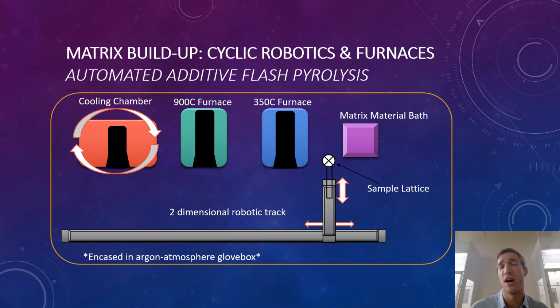Now, I mentioned this automated system that we're using for this project. Here is a basic schematic of how this system operates. It's enclosed entirely in an argon glove box that's positively pressured, and there are 4 different stages. The first stage is the material matrix bath, or smart syringe deposition, which deposits a diluted polymer precursor onto the sample, which is either a woven lattice of fibers or a single fiber tow. That is then moved on these 2-dimensional robotic tracks in 2 axes.